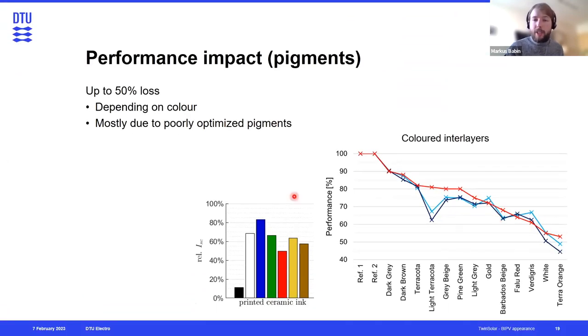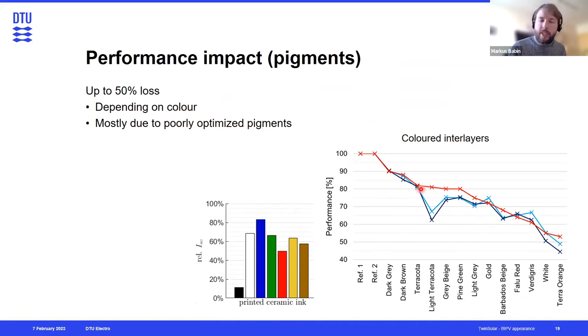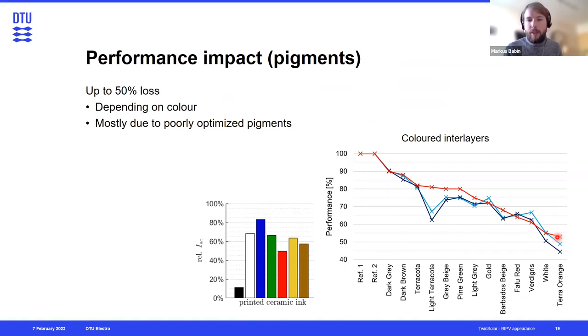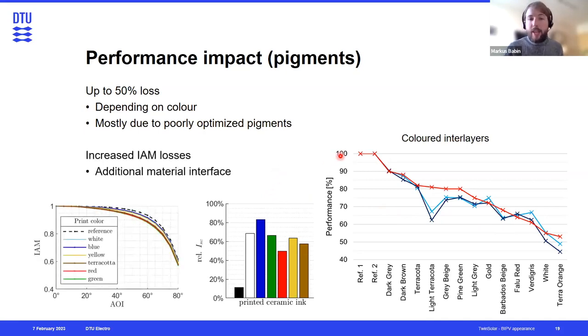Looking at performance of some measured samples with ceramic inks and colored interlayers: depending on the color and pigments used, we lose between 10–20 to 50% of the performance of our PV modules, because most of the sunlight is simply absorbed in the pigments and then partially reflected back to an observer. Additionally, we saw some additional IAM losses — increased reflection losses at higher incidence angles — because of an additional layer with higher refractive index in the module stack.